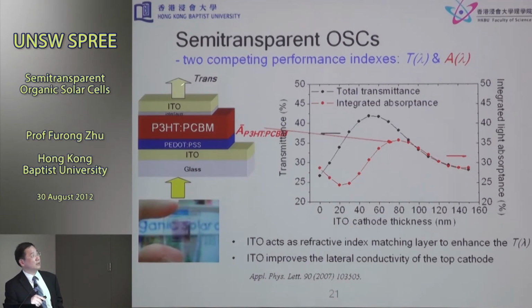So we know that without the upper organic stack, the transmission is essentially dependent on the ITO layer thickness. So we scan the absorbance of this layer as a function of the ITO layer thickness. Then we found that this absorbance in the layer modulates in this way.